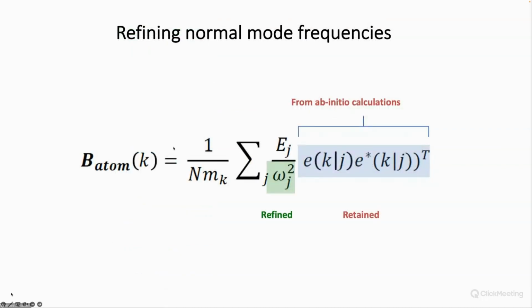So what we are going to do is to refine, instead of the anisotropic displacement parameters that we normally refine in crystallography, the frequencies of the low frequency lattice vibrations. We will retain these normal modes that describe the direction and amplitude of the vibration, and only refine the frequencies, which also alters the amplitude of the displacement in different directions.